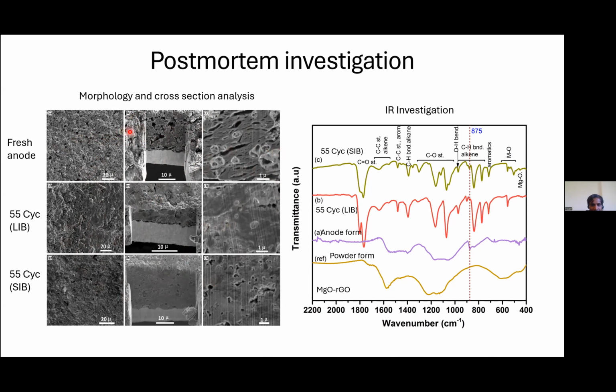The fresh electrode shows that it is a bit porous with stacked sheets of active material, and that's what is expected because graphene oxide, reduced graphene oxide with the pillared structure is expected to be like this, as the cross section suggested. And after several cycles, these are all filled, which is expected as well because of the intrusion of the electrolyte traces. Lithium ion battery, sodium ion battery, almost both are the same. There is nothing untoward or surprising, right? Everything is normal. And IR investigation tells, yes, this is good as well.